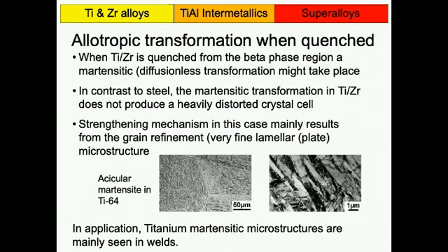So we often say the limit of optical microscopy is around a micron. It might be a bit better. In principle, it should be a bit better, but you should also always consider that the optics are never perfect. The lenses you use have some astigmatism. So 1 micron, maybe a bit better than a micron, is good. But if somebody tells you they've studied something with an optical microscope and they found that the grain size is half a micron, you should be very suspicious.